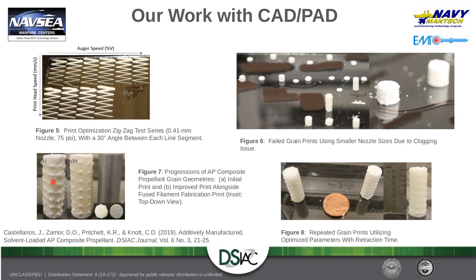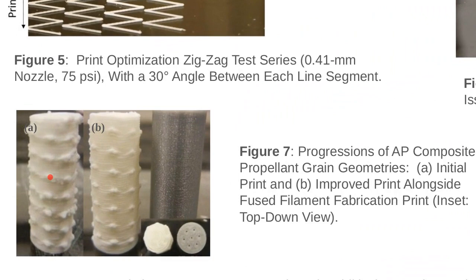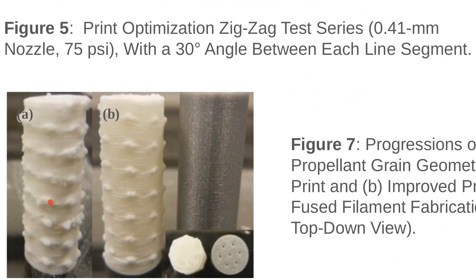However, another problem arose in which we would get these bumps on the side of our grains, and these bumps are an artifact of the printing process. Each layer has a start-stop point in which the printer will start dispensing and then stop dispensing at that same point, and those bumps are caused by excess material at those start-stop points. And that comes down to motor control of our dispensing assembly. Because the control method for the Techcon motor system is a bit strange, it made it a little difficult to properly control it.